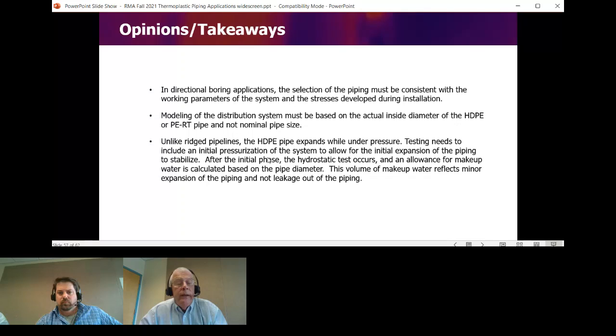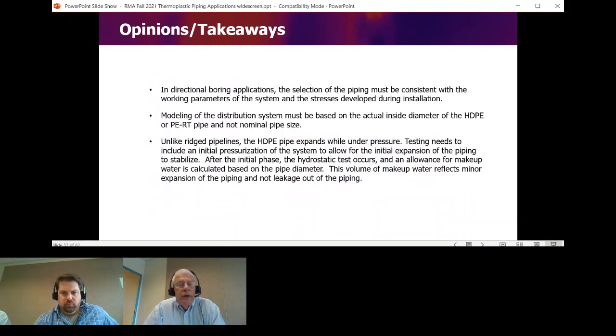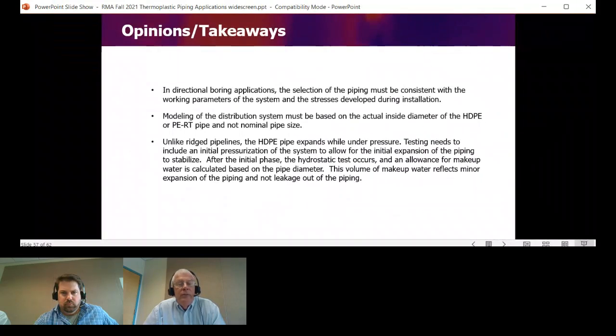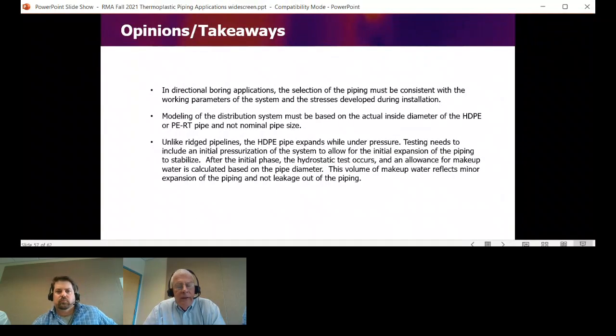Modeling of the distribution system, as we've talked about, is really based on the inside diameter of the pipe. Whether you're using any variation of thermoplastic pipes, as long as you account for nominal size versus the actual flow area, it shouldn't be a problem. There are a little bit of improvements in the C factors of HDPE. Typically the old code would use 130 for ductile iron, which DIPRA says should be 110. Some of the other plastic manufacturers say you should use 110 or 100, but I think using a coefficient of 110 to 120 should give you adequate modeling with adequate capacity.